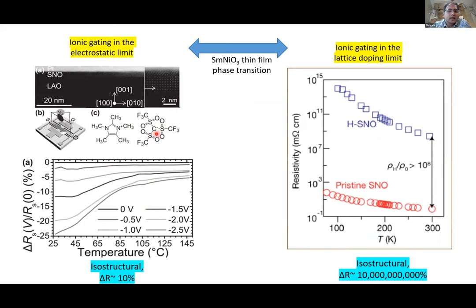This is electrostatic doping, or electrostatic transistors with ionic liquids. So this is the same compound, SmNiO3. And this is ionic gating at the lattice doping limit. So you see here, if you're strictly within the electrostatic limit, ionic liquids can only modulate the conductance of oxides like rare-earth nickelates by, you know, between 1 to 10%. And then if you exceed the electrostatic limit, then you can get, in this case for nickelates, some ridiculous number like 10 trillion fold or something like that. So this is what happens when you can dope electrons at this limit.